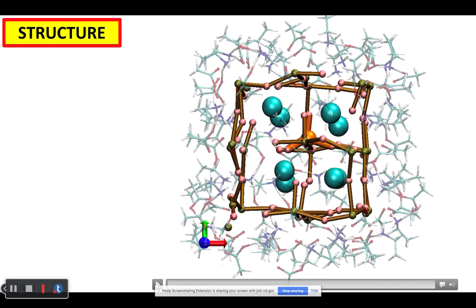So there is a slightly distorted cubic structure. The cyan spheres are cesium cations, and in the center there is a manganese doping. And this shell of anion and cation ligands push charge carriers inside and prevent formation of trap states. Okay, skipping.